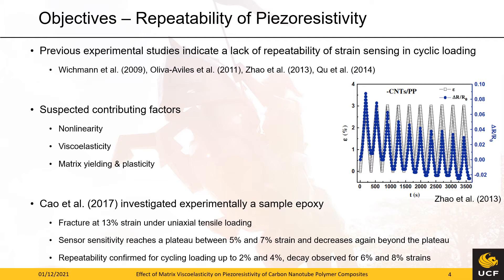These findings suggest a bigger influence of permanent matrix deformation on the sensor sensitivity than viscoelasticity. In order to prove this theory, the study will strategically investigate the influence of matrix viscoelasticity on the sensor sensitivity in the absence of permanent deformations with a previously developed representative volume element. The RVE is utilized to investigate two load cases under the two common assumptions for viscoelastic materials, namely a constant linear elastic bulk modulus or a constant Poisson's ratio.